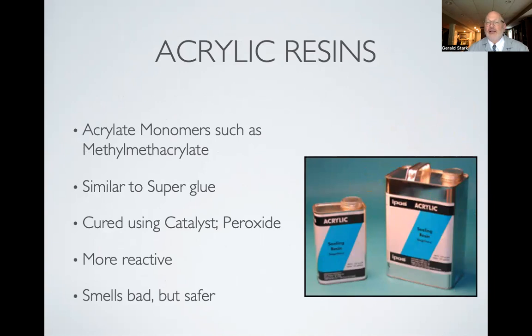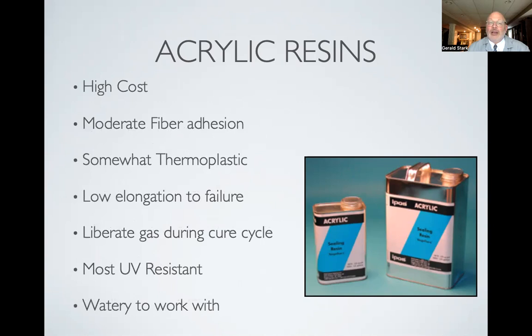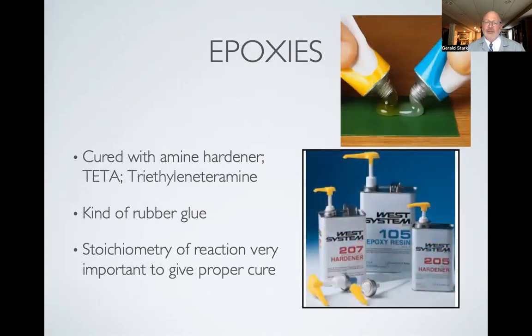It was more like a methyl methacrylate, kind of like a super glue, acrylic monomers, and it just used a catalyst and peroxide. It was still somewhat reactive and smelled pretty poorly, like seagull hearts in the morning, I remember. Although it was noxious in terms of the vapors, it was a little safer to work with. But it was pretty high cost, not very forgiving in terms of movement. So it was somewhat more like a thermoplastic, and some gas was liberated during the polymerization cycle. It was very UV resistant, but this particular acrylic that we used in lamination was pretty watery and difficult to work with.